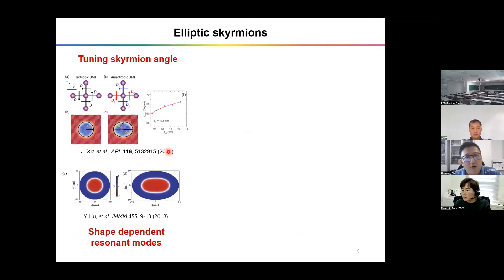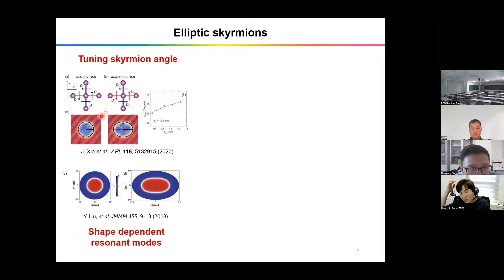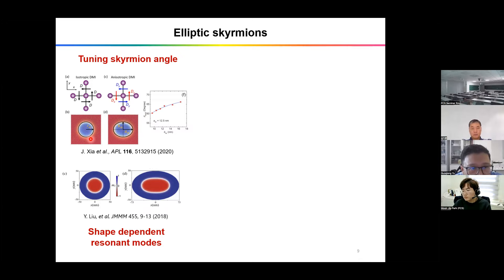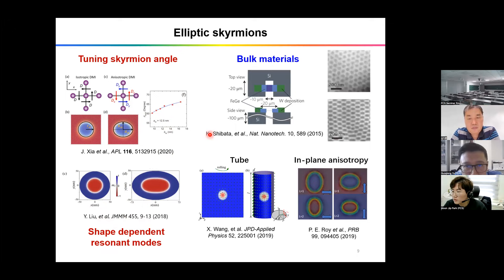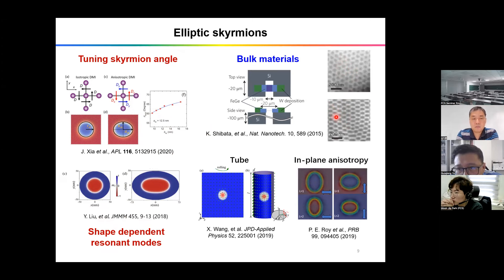For the material side, I will first talk about elliptic skyrmions. We are interested in elliptic skyrmions because of the skyrmion Hall effect — when we apply current, the skyrmion doesn't flow along the current; it is deflected in the transverse direction. By tuning the shape of the skyrmion we can change the skyrmion Hall angle, and changing the shape can also introduce interesting physics like novel resonance modes. People have realized elliptic skyrmions in bulk material by applying strain to the substrate, and simulations show elliptic skyrmions can also be realized by introducing in-plane anisotropy.